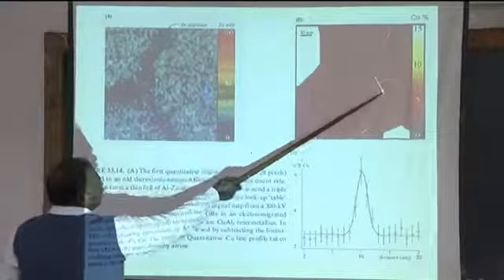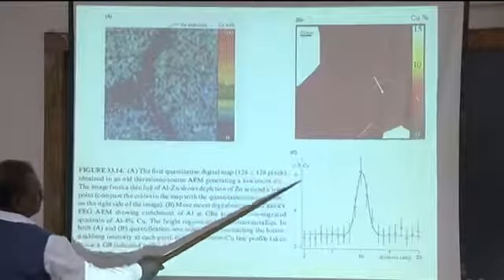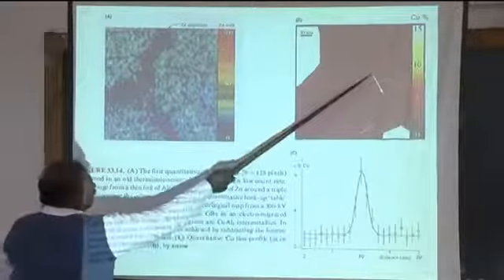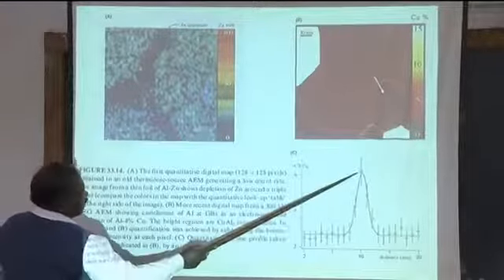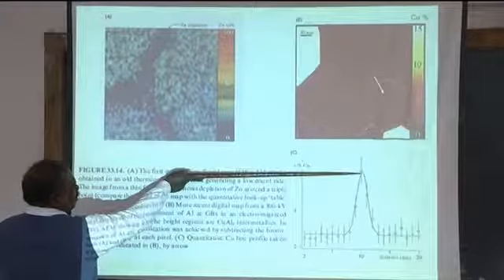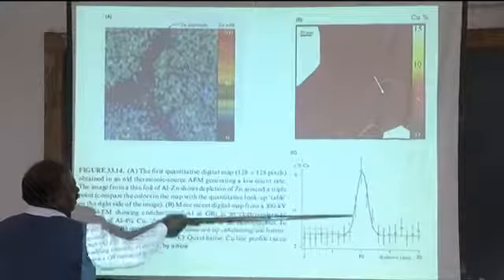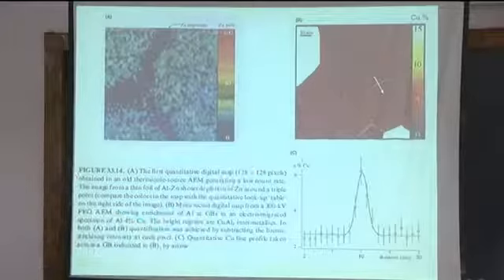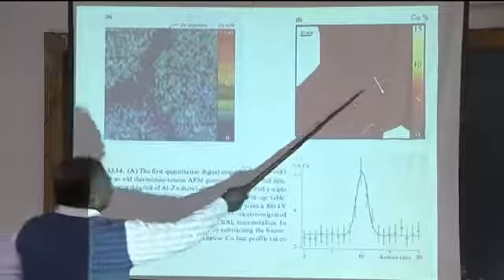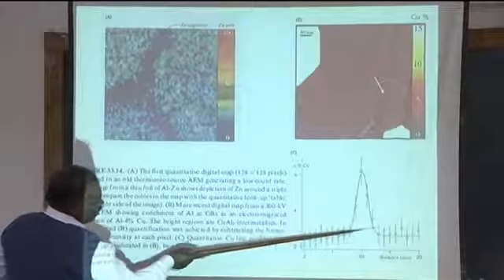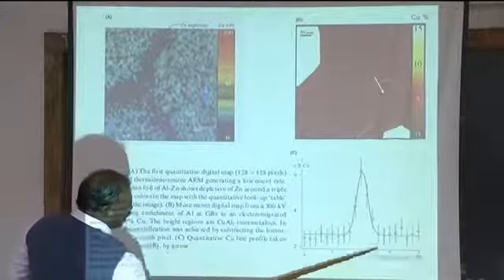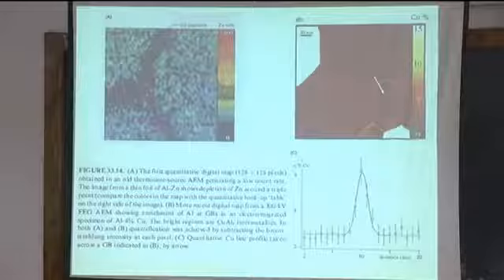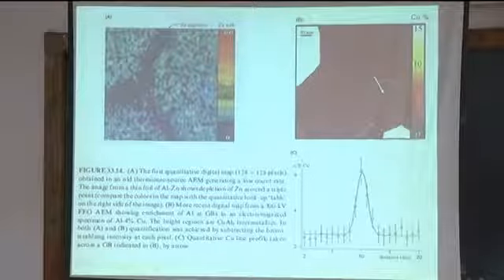And as you are scanning across here, you are looking for variation in copper atom percent. At this boundary, there is an enrichment that shoots up. At the grain boundary, the fraction of copper is more. Away from that, it is this much. At the boundary, it is this much. The segregation which is taking place there, you can study. What is this boundary which is showing the segregation? This is the dimension or width of the boundary. How many nanometers? You can see here, up to here it is 10 nanometer, 20 nanometer. This is a few nanometer, is the segregation. The analysis is possible, and these are available very much with our machines.